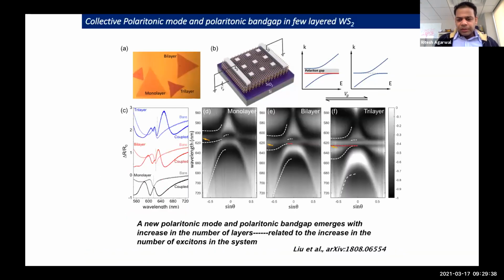And then one last thing before I move to the polariton to topological case. What Wenjing did was also show that if you have a monolayer, and you go to bilayer or trilayer, since the physical spacing between the layers is very small, all we are doing is packing more excitons, so the exciton density increases within the plasmonic mode. What she saw was very interesting.